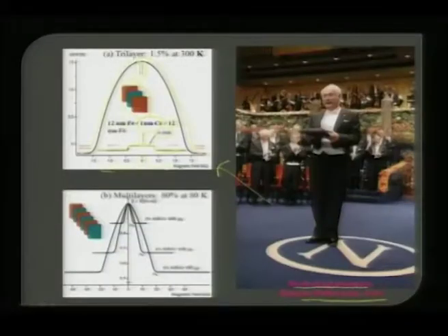Now as you sweep the magnetic field in both directions, you see that these two moments get ferromagnetically ordered in this fashion, and at that point the resistance is really low. The same way it happens if you flip it to the other direction. Therefore, there is a tremendous fall in resistance as you sweep the magnetic field. Suppose you can keep reverting this at a very low field, then it becomes a real magnetic switch.